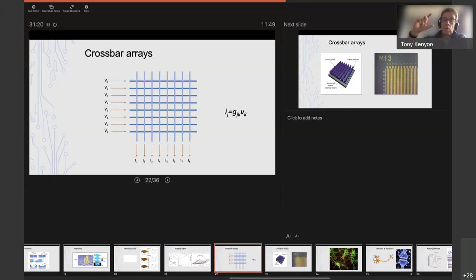And these devices go by many names. You may have heard them called memristors, resistive RAM devices, resistive switches. I'll call them memristors because these are devices whose resistance depends on their past history, what voltages have been applied, what currents have flowed. So if we imagine at each of these cross points here, we have one of these memristors, and we're able to, in an analog way, vary the resistance of each of those memristors, then what we can do is we can actually program into this array a series of numbers, analog numbers. So each of these cross points has a different resistance. And then if we apply, in this case, a series of voltages to all of these horizontal lines, let's call them word lines, and then we measure the current coming out of each of these vertical lines, let's call them bit lines, then what we get is each of the currents here is the sum of all of the voltages multiplied by the conductances at each of the cross points here.